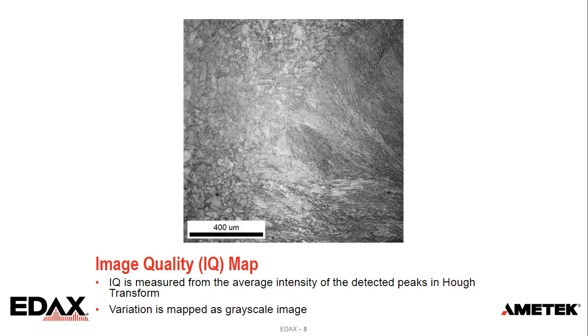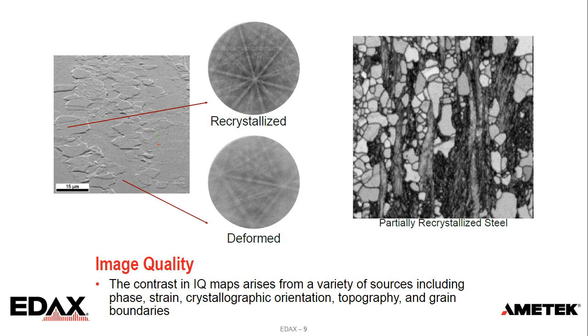And we can see an example of this from a different steel. This is a partially recrystallized steel. IQ map contrast can come from phase contrast. That will just be difference in scattering from atomic number. It can come from, the generic term is strain. But as we deform the lattice, the diffraction is not as sharp, so the peaks are not as bright. Crystallographic orientation, some orientations will have more lines or more poles in it, so we'll end up brighter in the Hough transform.